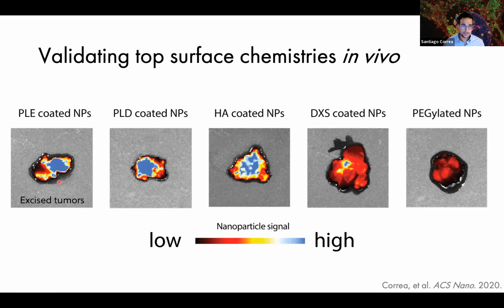And what we can see is very clear higher levels of nanoparticle accumulating in these tumors for our carboxylated systems. So polyglutamic acid, polyaspartic acid, and hyaluronic acid-coated nanoparticles. And that's in contrast to our dextran sulfate-coated LBL system, as well as a pegylated control nanoparticle system. And so overall, this was very exciting to us since we were seeing these benefits both in vitro and in vivo. The question that I wanted to ask at this point is, what are these different carboxylated nanoparticles doing after they bind to these cells?